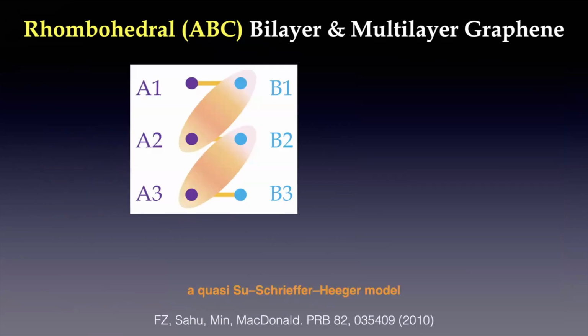So what is the rhombohedral graphene system? This is pretty simple. It's like a quasi-Su-Schrieffer-Heeger model. Think about it: in each layer we have A and B sublattices. There is an interlayer coupling. The leading interlayer coupling is between the first layer B and the second layer A, because they are directly on top of each other. The energy scale is 400 millielectron volts.